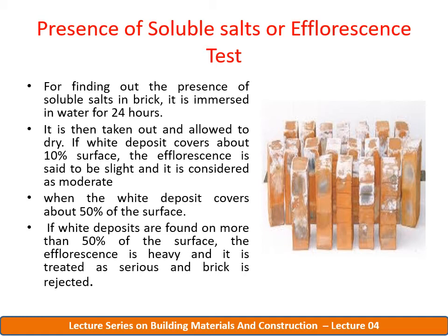Moderate, when the deposit of efflorescence is heavier than slight and does not cover more than 50% of the exposed area of the brick surface. There should not be powder or flake on the brick's exposed surface.